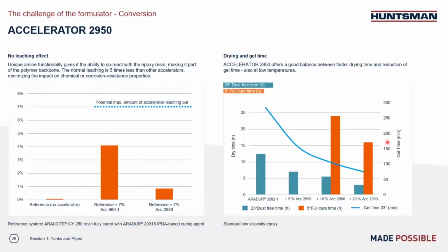So on the chart on the right side, we see how using this accelerator can improve the curing, especially at the lower temperature. If we look at the room temperature curing condition first, you can see at 23 degrees the dry to touch time without any accelerator, in this particular system, is about 12 to 13 hours. But by adding a 5% loading amount, we can drop to almost half, 7 hours.